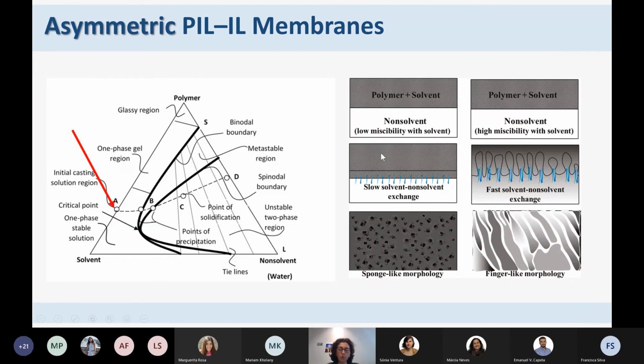So in fact, what we are trying to do is enter here where I have the polymer dissolved in the solvent, and we use a non-solvent. When we use a non-solvent, our system starts to go from this point here, enters the two-phase equilibria, and at the end of the day, when all the solvent and the non-solvent is exchanged, we end up here, we end up in the D point.